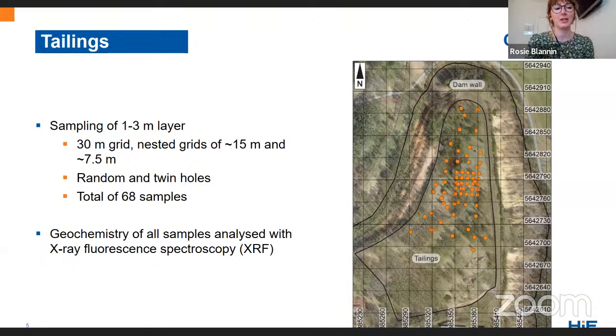So we first performed a sampling campaign on the tailings. And this involved sampling the 1 to 3 meter layer, so just a shallow zone of the tailings. And we have these samples where the orange points are on the map, on a 30-meter grid, nested grids of 15 meters and 7.5 meters, with additional random and twin holes. And in total, this is 68 samples. Unfortunately, we couldn't sample this southern part of the tailings, because there's a lot of rubble and construction materials on the surface that we couldn't drill through. We then analysed all of these samples for geochemistry.